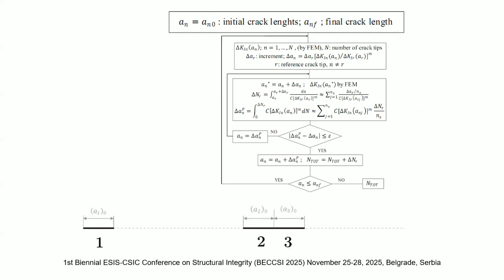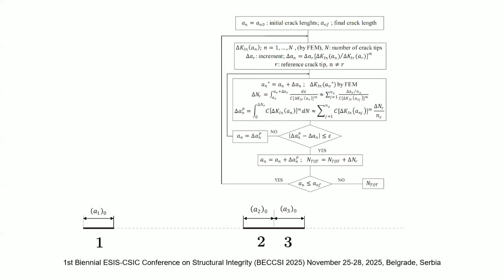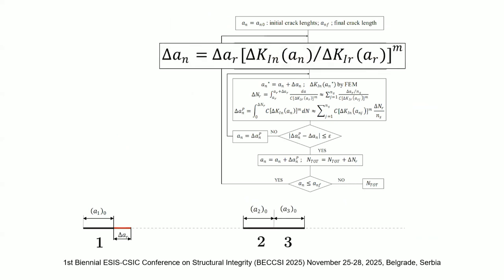And so this is what we have as a first one from our experiment. Then we give some initial increment for the reference crack tip, and then we assess increments for the other two crack tips by using Paris law in this way. A good way to do it. Then we have this assessed increment for crack tip 2 and crack tip 3.